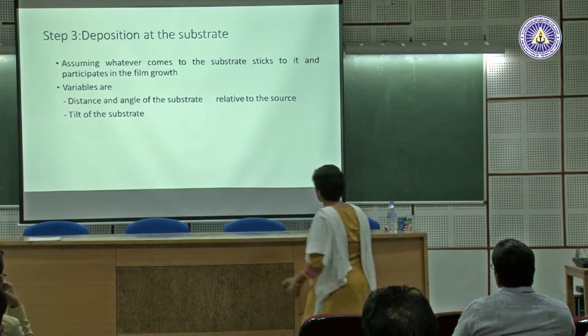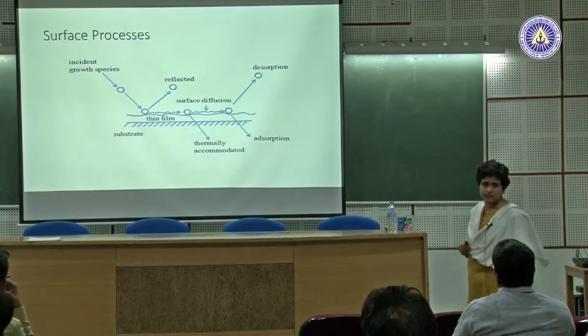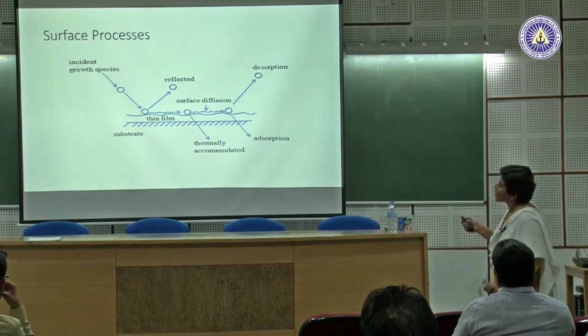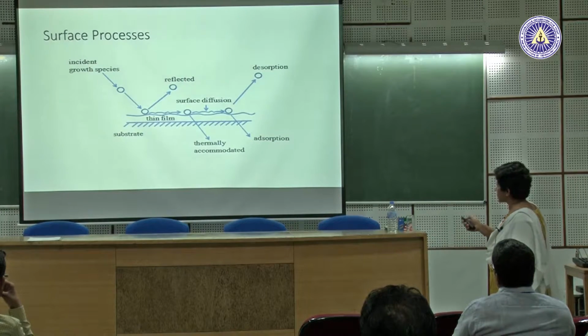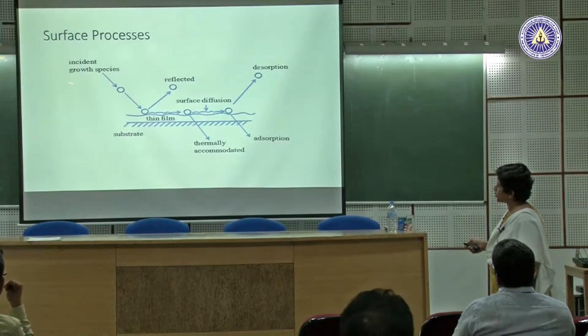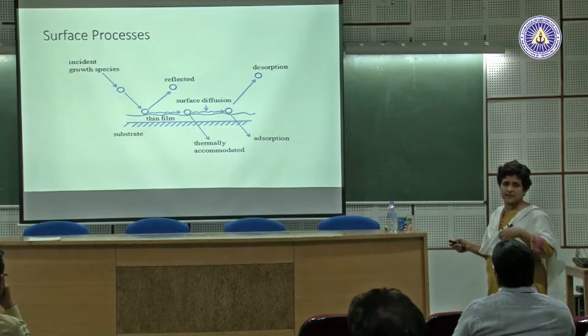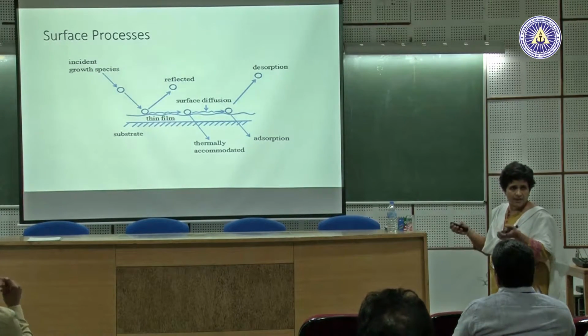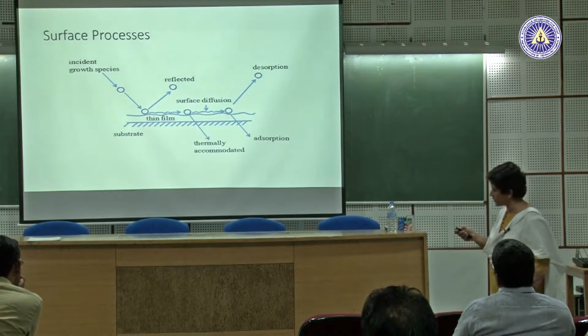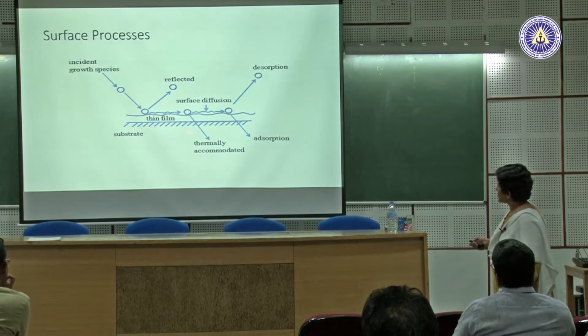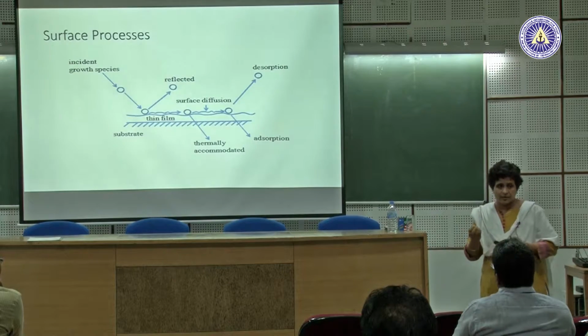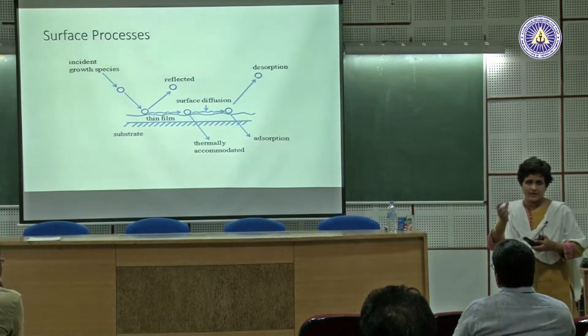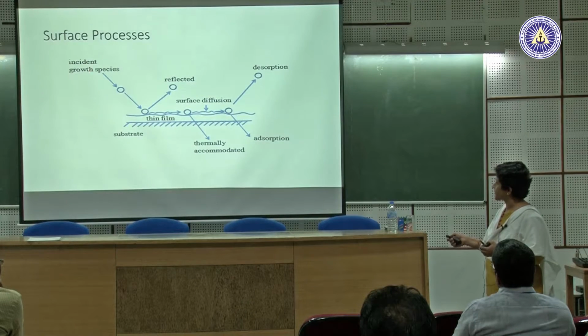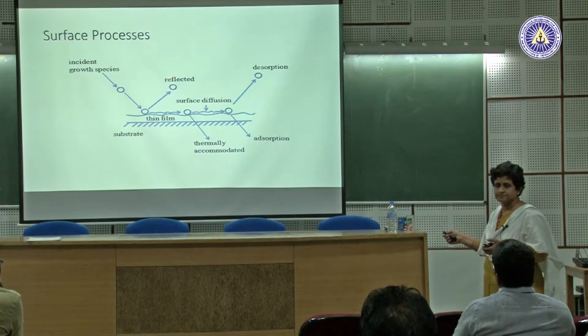So, what are the parameters that will decide that? This is what will happen on your surface. This all can happen, or maybe one or two can happen, but let us just go through the process. You would have an incident growth species, which is what we have created by either E-beam or thermally heating it, which could be in atomic form or molecules or ions. It comes to the substrate. Remember, it is evaporated, so it has some thermal energy higher than the thermal energy of the substrate. So there is a good chance that it does not become part of the film and it gets reflected.